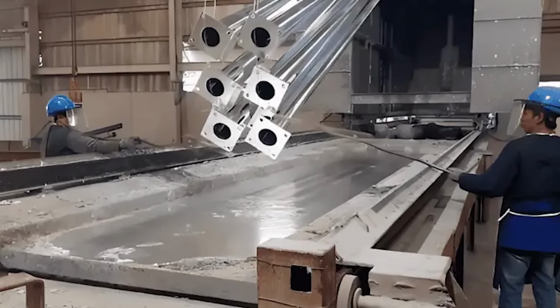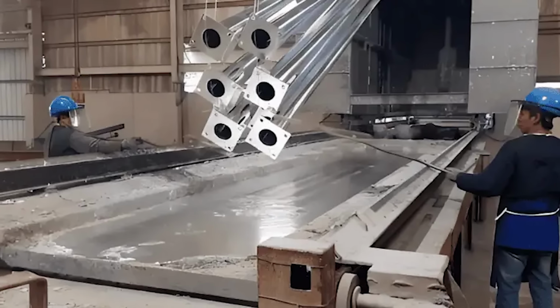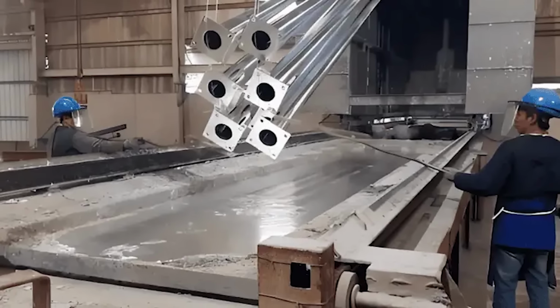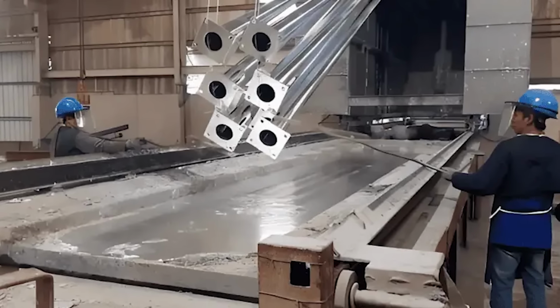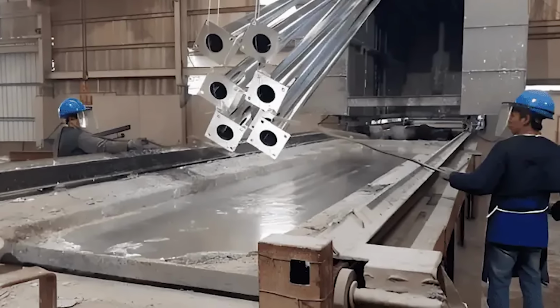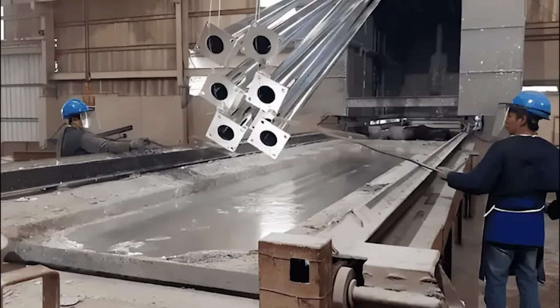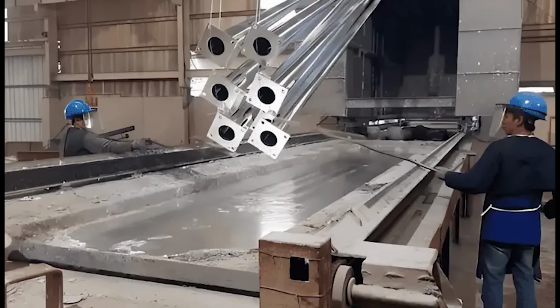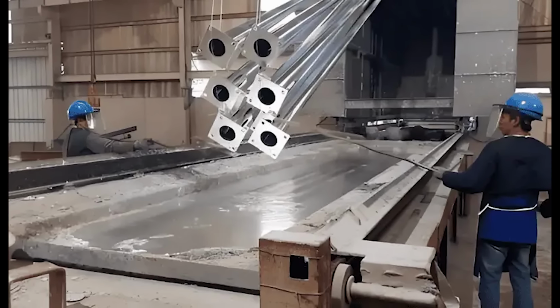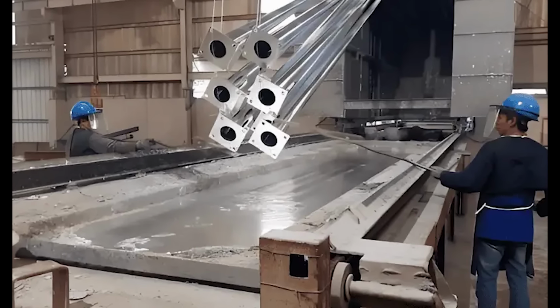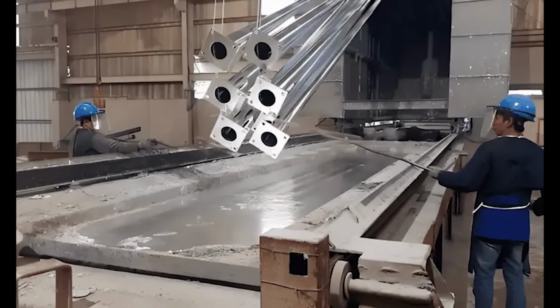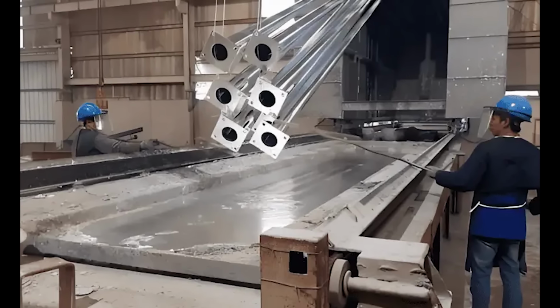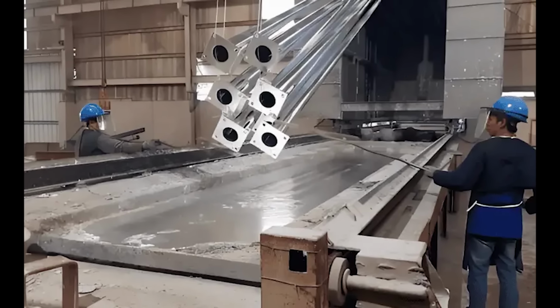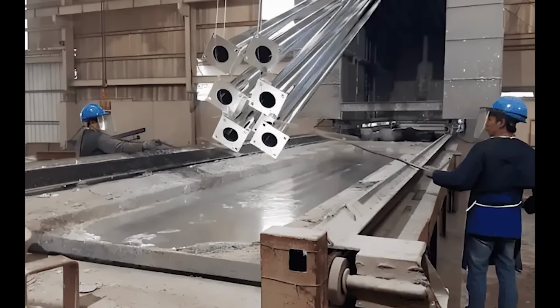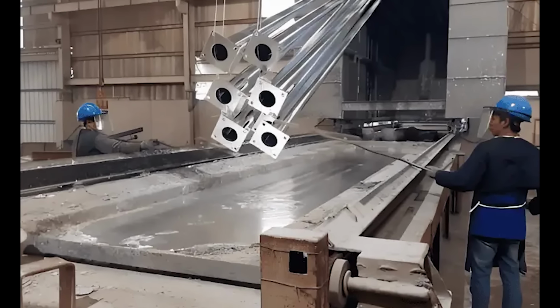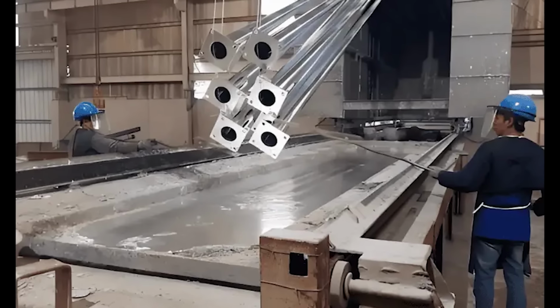The mathematical reality of coating thickness became visible in cross-sections of test samples. Heavy structural galvanizing, applied through batch hot dip processing, created thick alloyed layers that could resist decades of exposure. The multiple ounce coatings common in 1870s bridge construction contrasted sharply with modern practice, where continuous galvanizing lines and electrolytic processes prioritize smooth surfaces and fast throughput over maximum thickness. Batch processing moved slowly but built substantial protection.